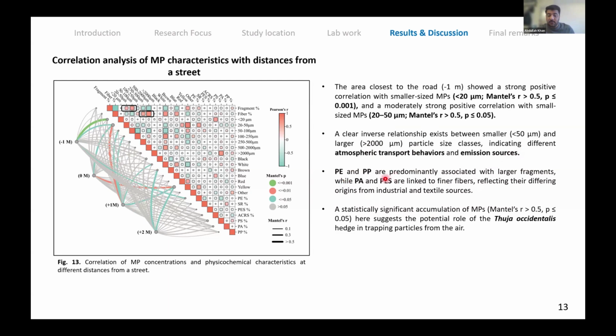Additionally, polyethylene and polypropylene are predominantly associated with larger fragments, while polyamide and polyester are linked to finer fibers, reflecting their different origins from industry and textile sources. A statistically significant accumulation of microplastic here suggests the potential role of Thuja occidentalis in trapping particles from the air.